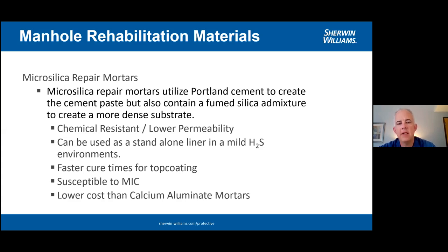It's very fast. With standard Portland cement, you cannot put coatings and linings back on them for 28 days minimum. With the microsilica repair mortars, we can cure it one day and then coat back over it with the protective lining the next day. So it's a very fast cure time for top coating.